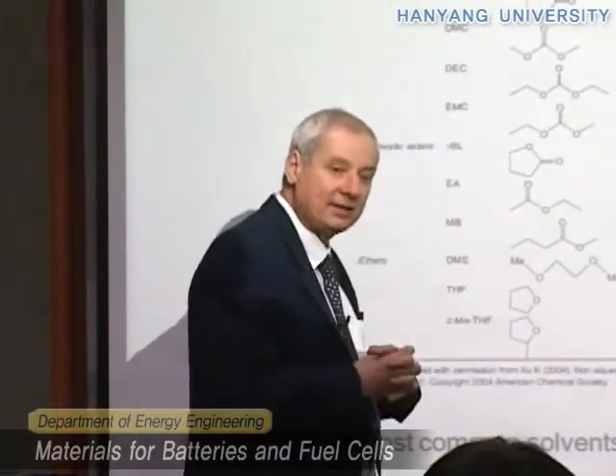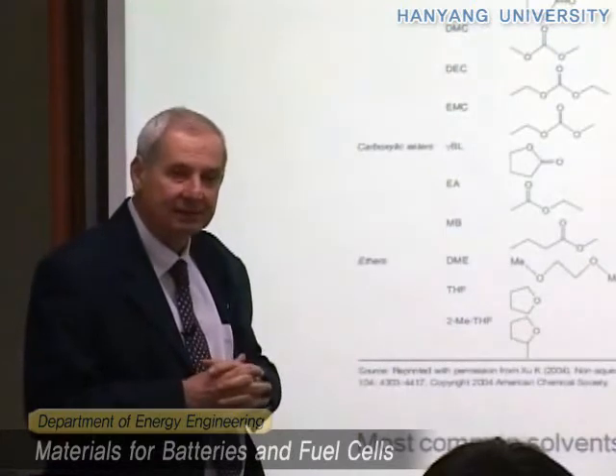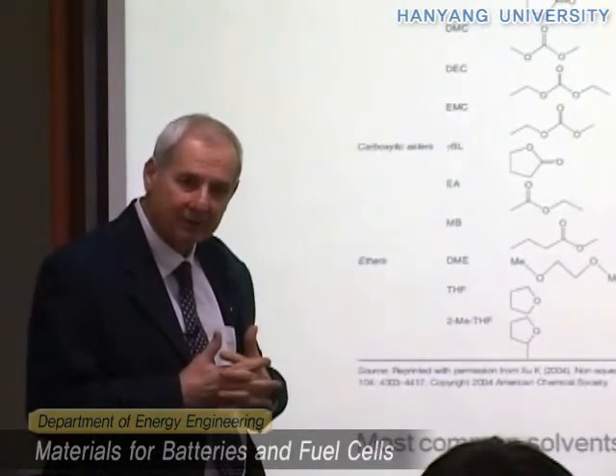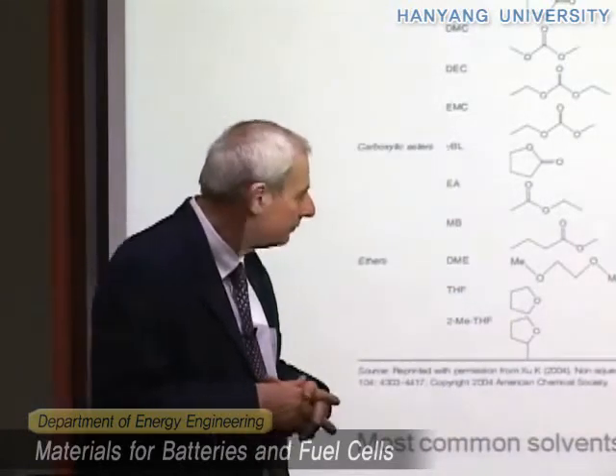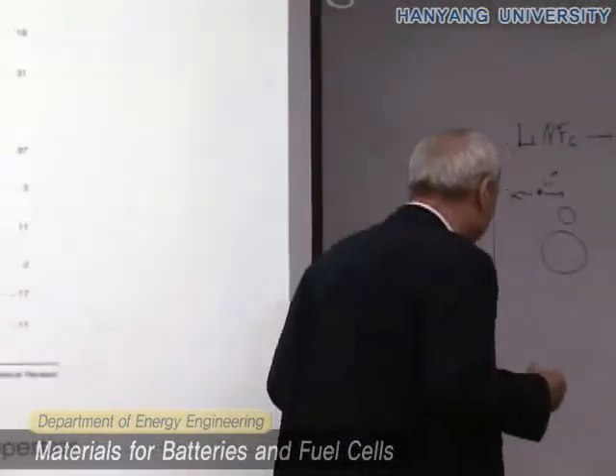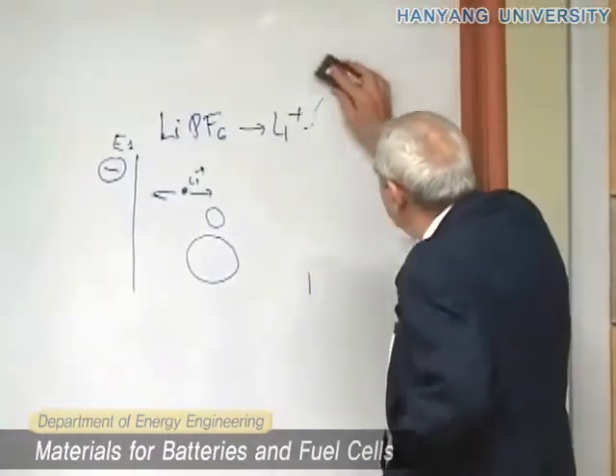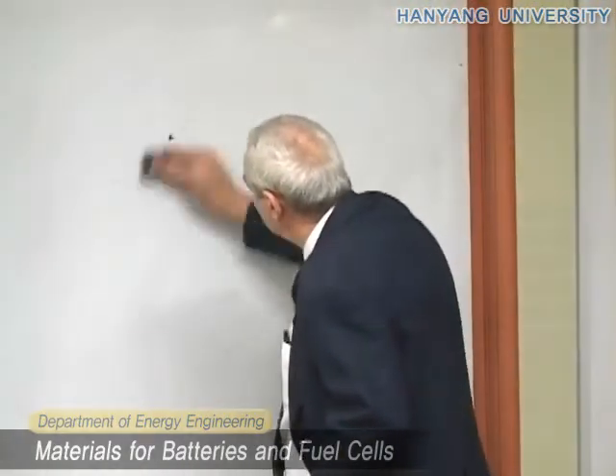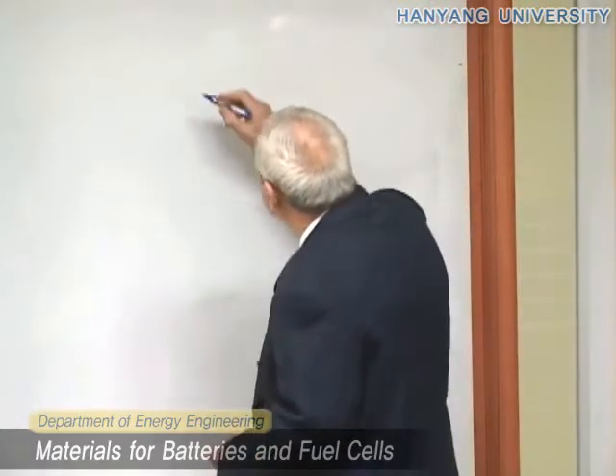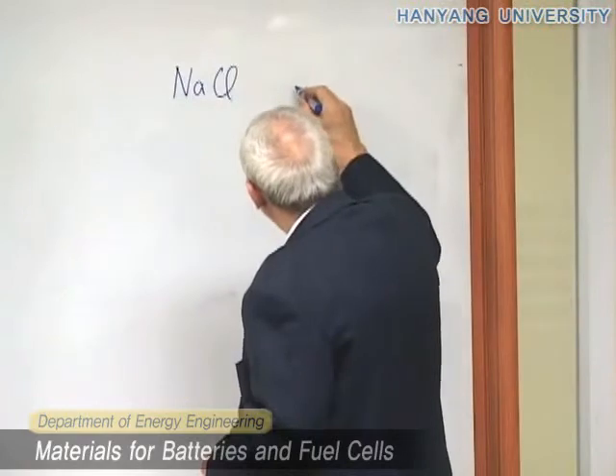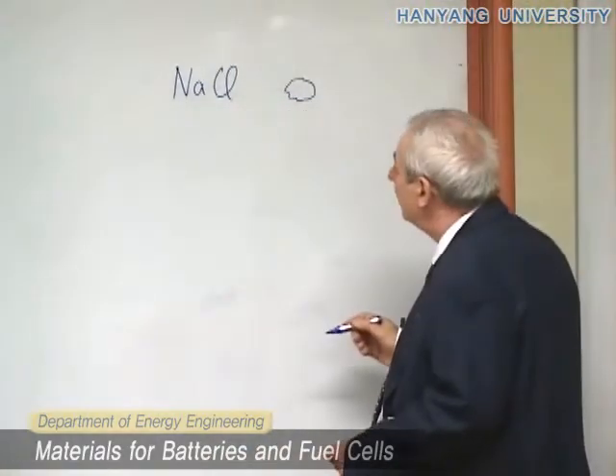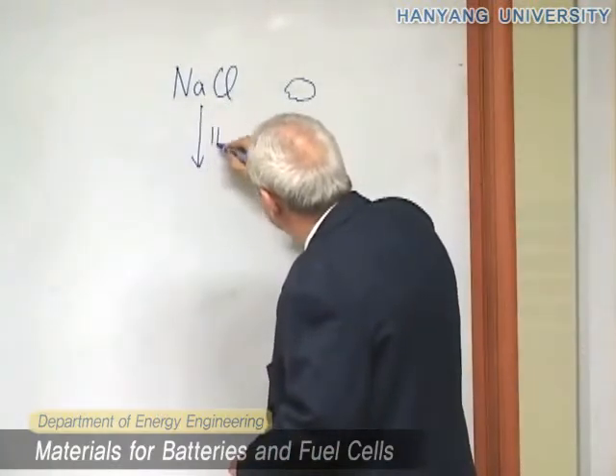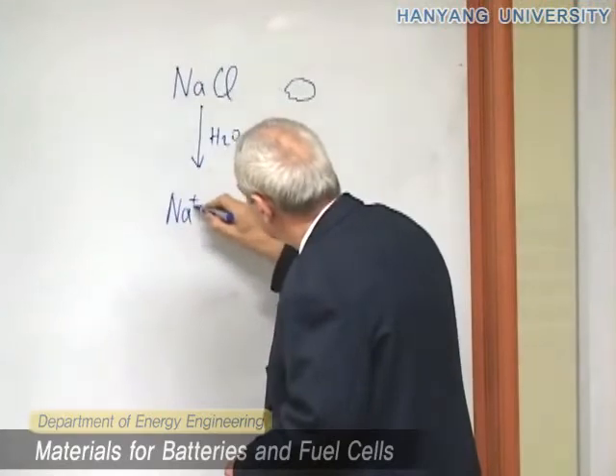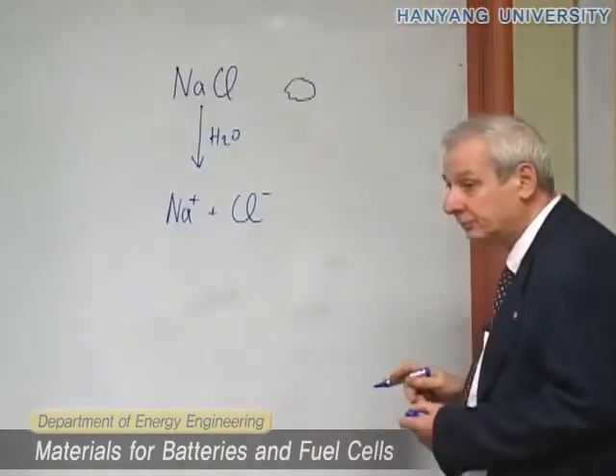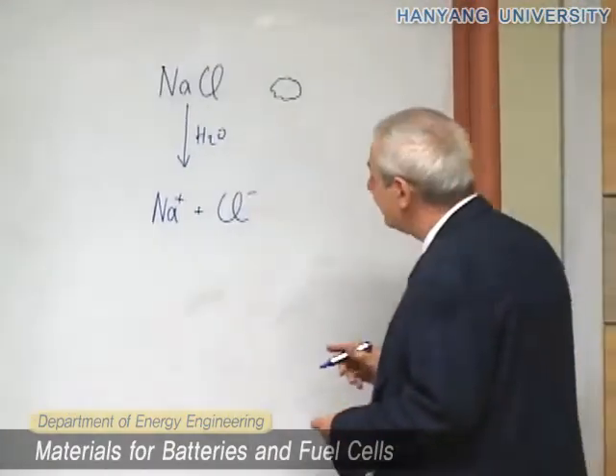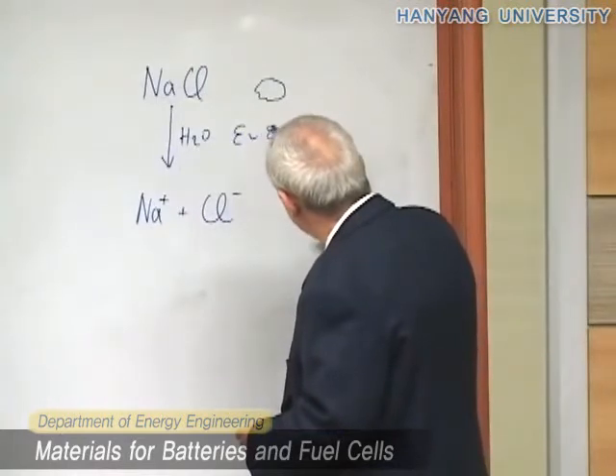Then the dielectric constant is very important. Why? Because the highest is the dielectric constant, the highest is the dissolving power of a solvent. For instance, just to give you an example, many very well known to you, just to explain this, suppose that you have a salt like this. This is a solid, right? But when we add some water, this becomes a solution. And this happens because water has a very high dielectric constant, about 80.